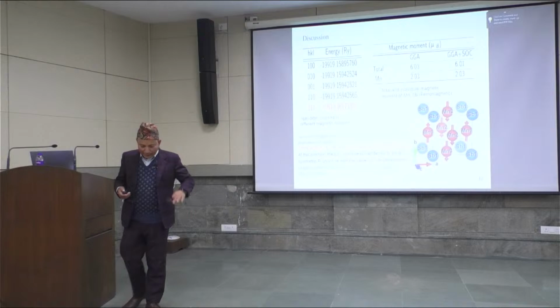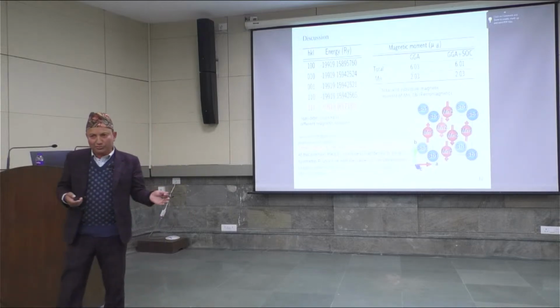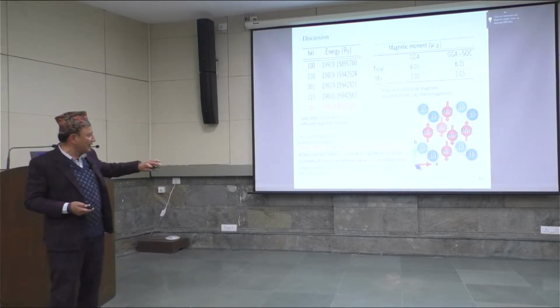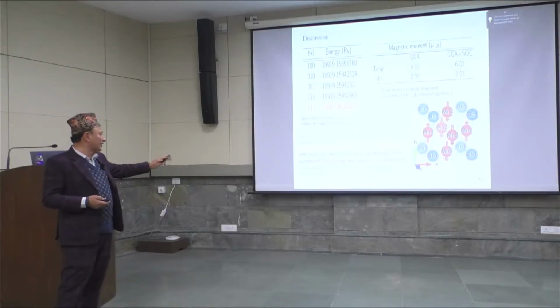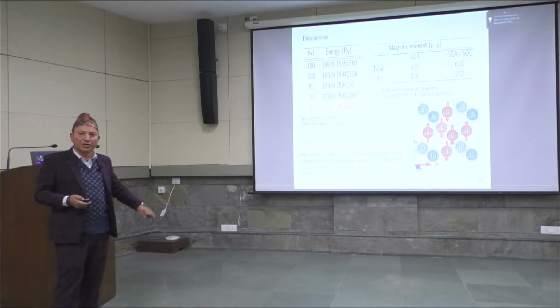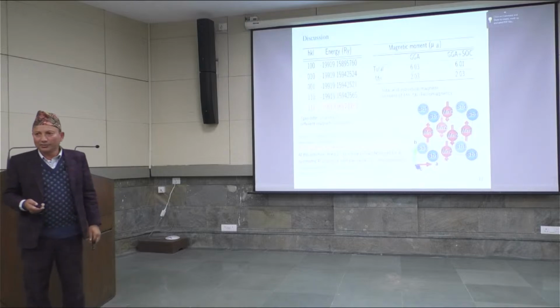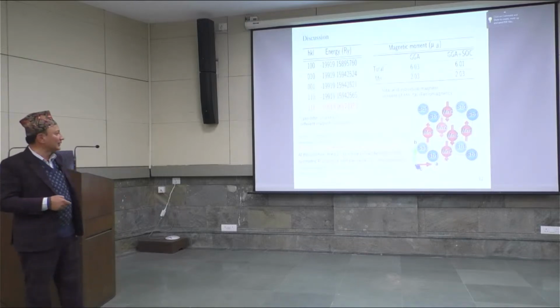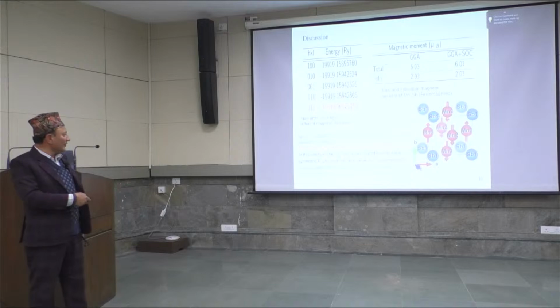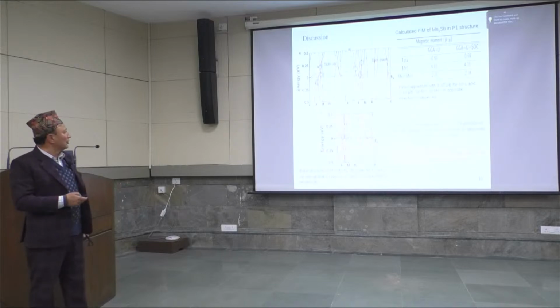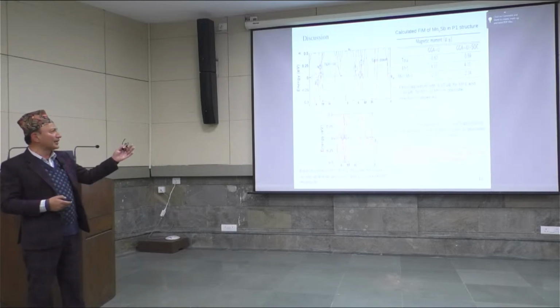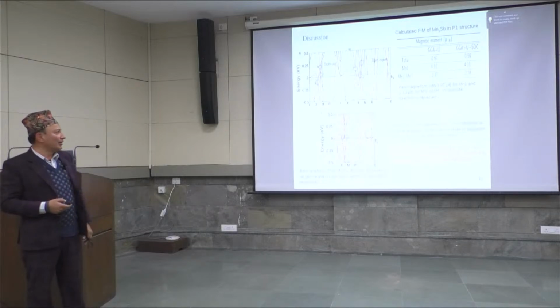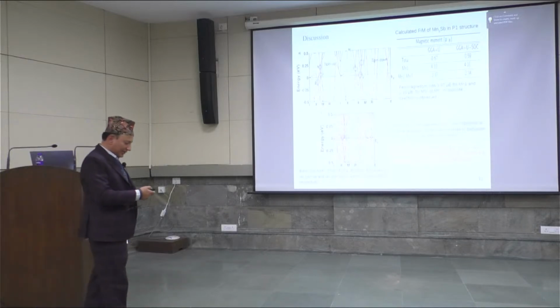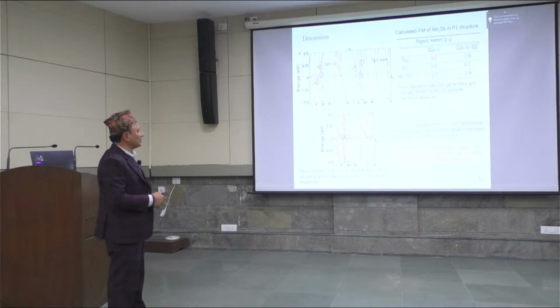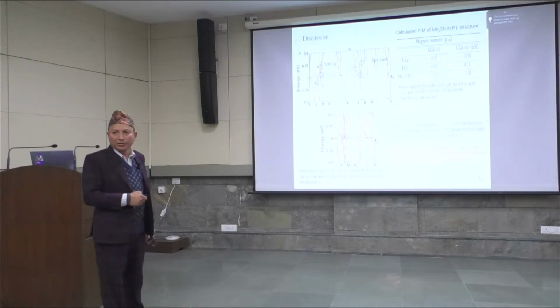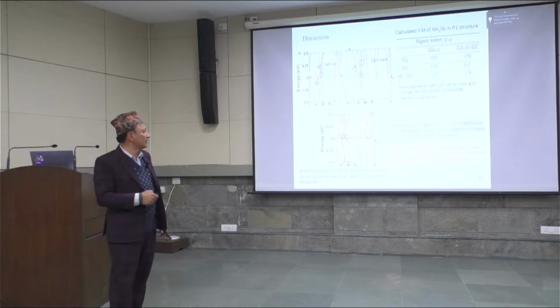To do that, we transformed the L10 structure to the P1 structure, and then used U. In our effective model, we used U effective as 4 electron volts for the Mn1 site, not on the other Mn sites. After using this, we get the ferromagnetic result with 3.97, and this is the result we obtain as given by the neutron diffraction experiment.